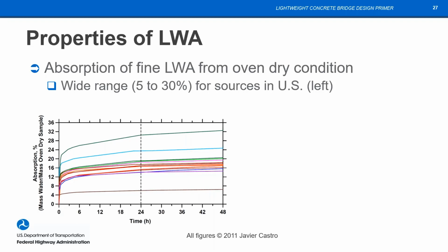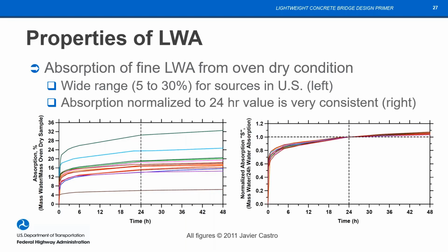Here's some data just for an example. This is absorption data. You're seeing a number of different sources. Pretty much all the sources in the US for lightweight aggregate are on this plot. And you can see that at 48 hours over on the right side, the absorptions are ranging from about a little over 6% all the way up to a little over 32%. But it's an interesting fact that if you normalize all this data to the 24-hour value, the behavior of all these different aggregates is really very similar. They gain absorption very quickly, and then it flattens out and continues at a much slower rate.